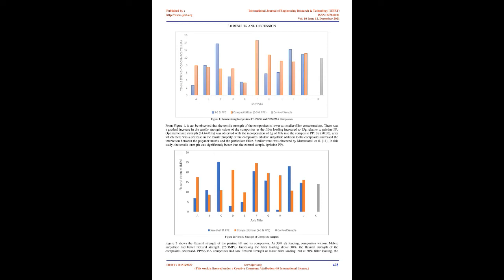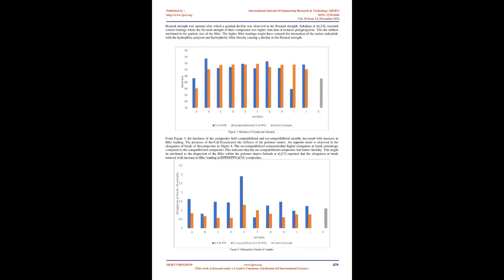2.3 Tensile strength and flexural strength. Mechanical properties of the blends were investigated using a computerized universal testing machine, Instron Series 3369, with a load cell of 50 kN, ASTM D638/D790. A 3-point bending test was used to determine the flexural strength. The span length was 65 mm. The dimension of the specimen for the tensile strength was 70 mm by 5 mm by 15 mm.